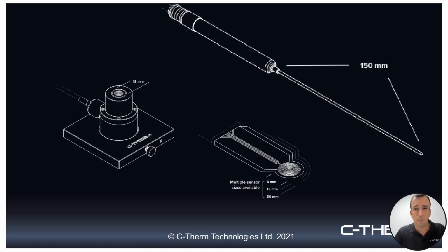One of the things I really like about the Flex TPS sensors, they also bring in some additional capabilities for testing thin films, for testing anisotropic materials. So if you're dealing with an oriented structure where the heat flow patterns may be different in the different orientations, through plane versus in plane, some really strong utilities available with the TPS. And it's available in different size formats. It's 6, 13, and 30 millimeter diameter sensors.